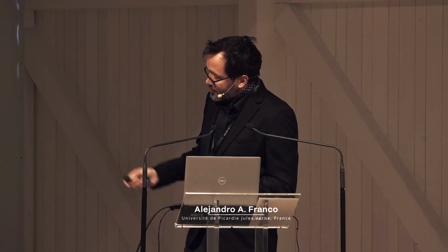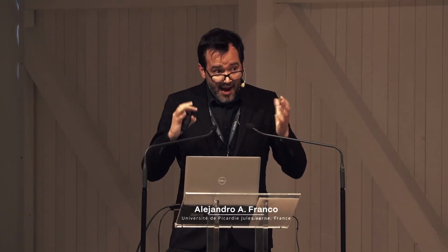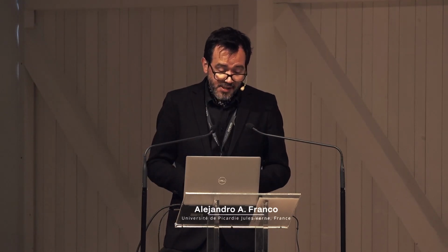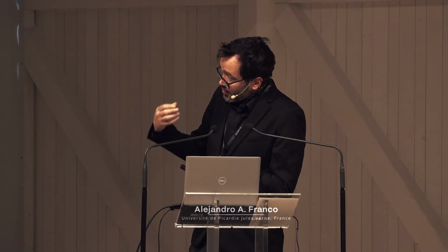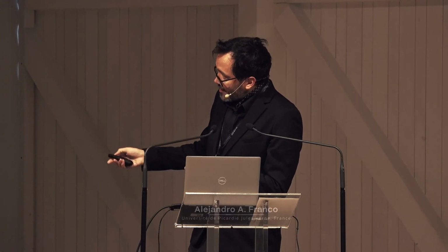Well, this is something that we also simulate, and at the end, you get a virtual 3D representation of these electrode microstructures where you can nicely see where the active material particles are located, where the carbon, the binder, the pores are located, and so on and so forth. You need porosity also inside the electrodes, because you need a liquid electrolyte in order to ensure a proper lithium-ion exchange between the two electrodes that you have in a lithium-ion battery cell.